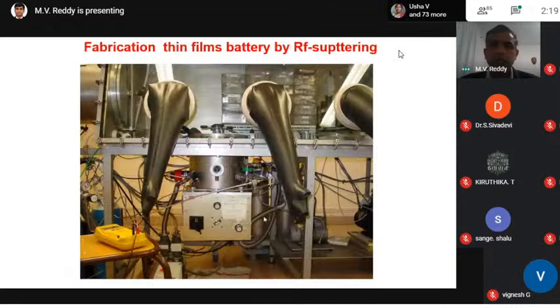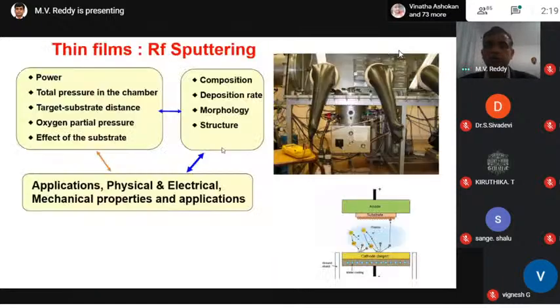So there's a typical sputtering unit. Suppose you want to get thin films with hygroscopic materials, we can press a target, do the sputtering, and you can open the cell inside the glove box. Interestingly, as a physicist, you can vary a lot of physical parameters, the power, pressure, the composition, deposition rate, etc. Again, depending on the physical, electrical and mechanical properties and the applications, we can do this.